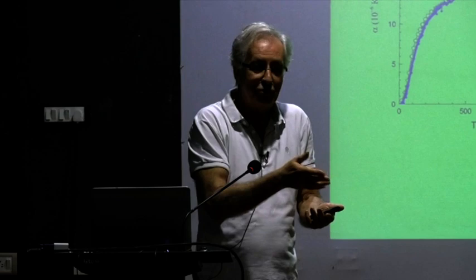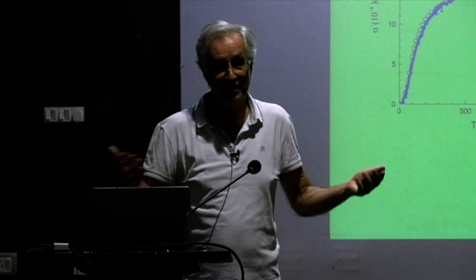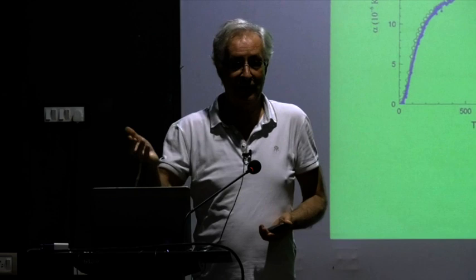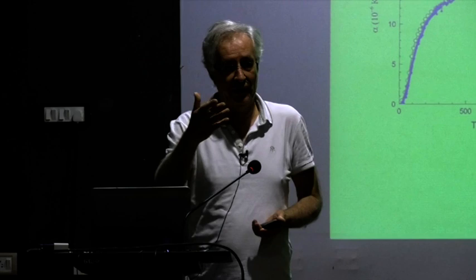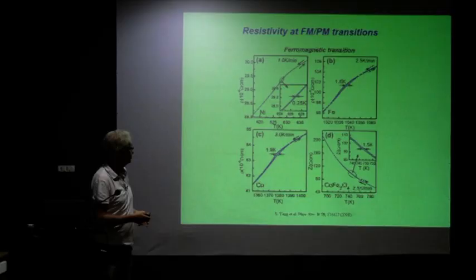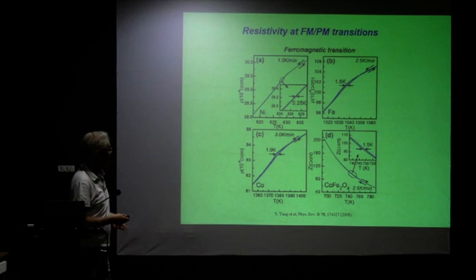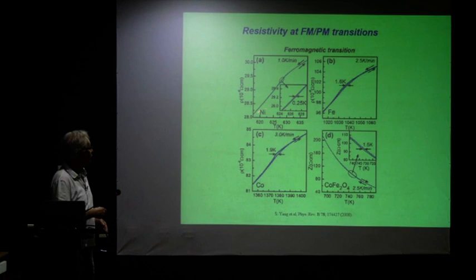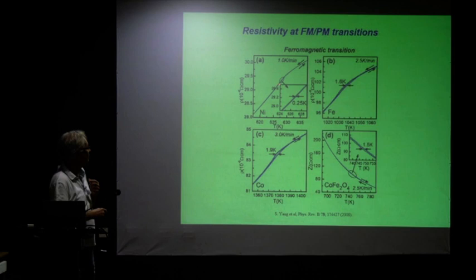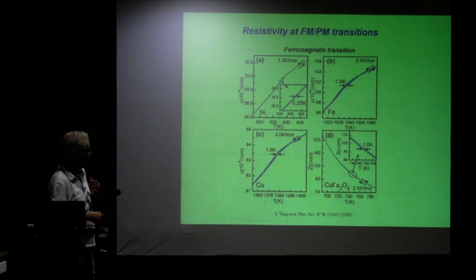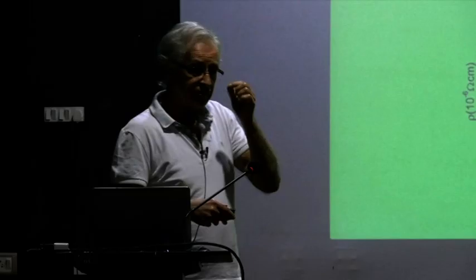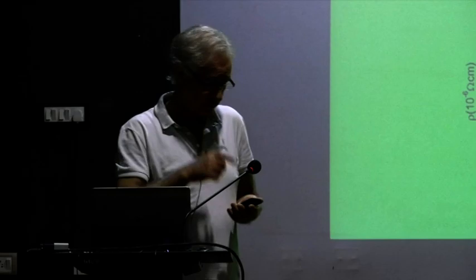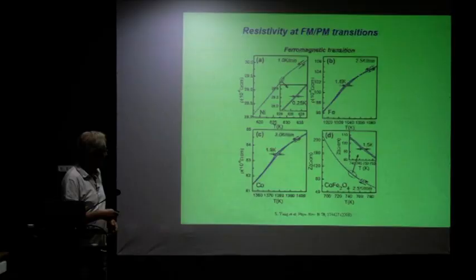Theories will still work up to the second order transition, but if you start measuring critical exponents and trying to fit theories, certain questions arise: what have people been measuring as critical exponents at temperatures close to Curie temperatures, and with which theory are you fitting? Because you're measuring something at a first order magnetostructural transition, and the theory is made for a second order transition. So be careful in the future when talking about first and second order transitions. Very recently — in 2008 or so — a new paper reconsidered all of this. They went and measured the resistance at high temperature of nickel, iron, cobalt, and a cobalt ferrite reference material. Within experimental resolution, they find that there is always hysteresis involved with these transitions — you never get away with it.